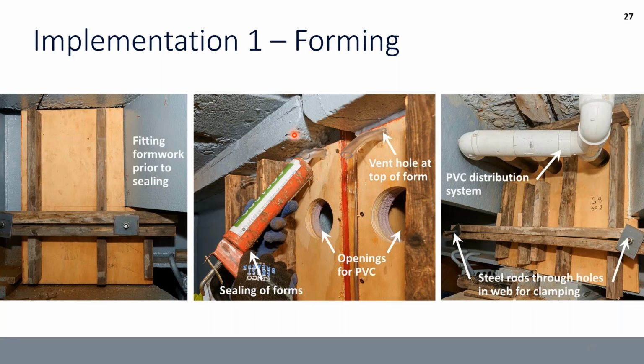So for those of you that worked with UHPC, we did specify a watertight formwork, and it's because once it starts going, it can be really challenging. So including these ties really helped us with not getting any explosive blowouts. And that was a huge concern since we were over the rail. And then this PVC distribution pipe went straight up to the bottom of that deck core.